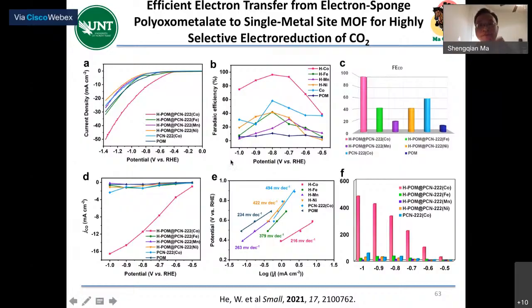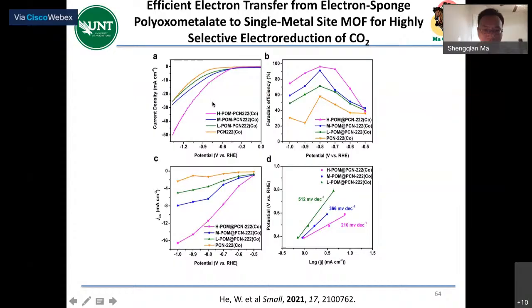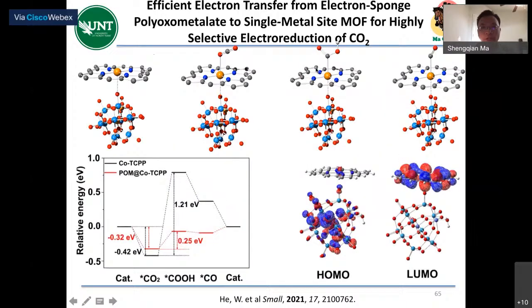We did this with different loadings, and we found we can achieve very high Faraday efficiency, over 96 or 98, and the Tafel slope is also very small, and it's very selective in reducing CO2 into carbon monoxide. This is the different loading, high loading, low loading. The high loading, of course, is the best as well. And the Faraday efficiency, the highest one we can reach is 98. And this is the mechanism I just mentioned. We put this electron sponge in the MOF cavity. They can supply electrons to the cobalt. There's some interaction, a very weak interaction. And this can direct the electron transfer and then improve the Faraday efficiency.